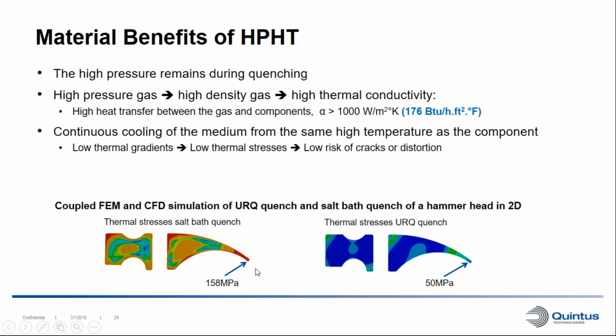If we look below here, we have a stress plot, and this is for a coupled FEM and CFD simulation of a URQ quench and a salt bath quench. And these were made for a hammerhead in 2 dimensions. So if we look at the simulation of the salt bath quench, we get relatively high thermal stresses in some areas of this component. And then comparing to the same kind of quenching in the URQ HIP, we can see that the thermal stresses are significantly lower.